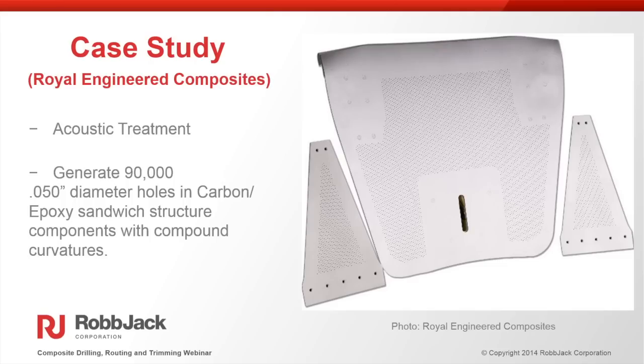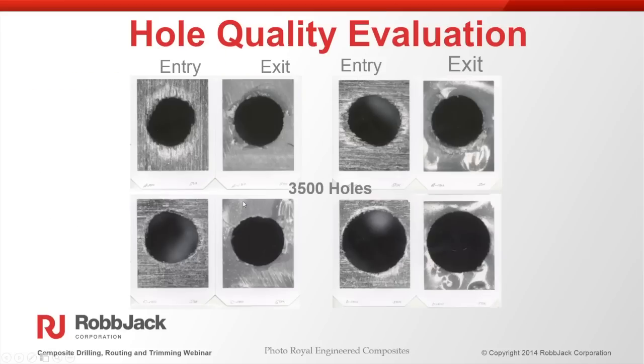And we developed an excellent solution for this. Essentially what they're looking at is when they do these holes, they need very nice part integrity, and the holes need to be nice and round, as well as not have any kind of delamination. So what you're seeing, all these holes are showing the entrance on the left, exit on the right, at 3,500 holes after the tool had cut 3,500 holes.